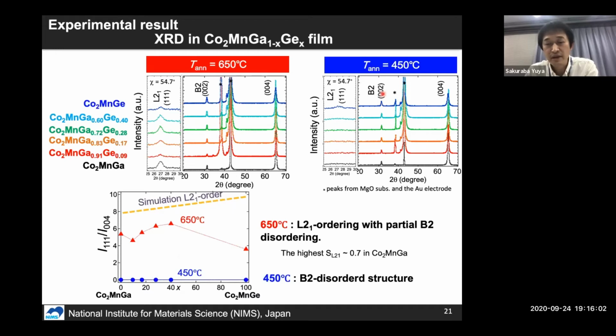So we can conclude that these films have the B2 disordered structure, not the L21 ordered structure. But as you can see on the left side, when we increase the annealing temperature to 650 degrees C, we can clearly see the L21 ordered 111 superlattice peak.